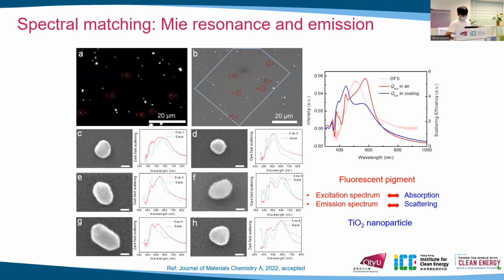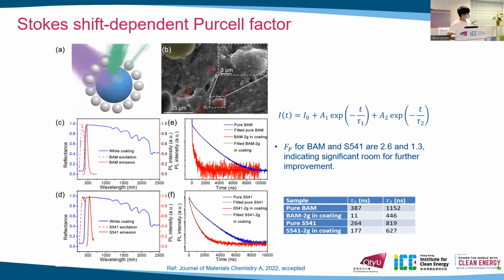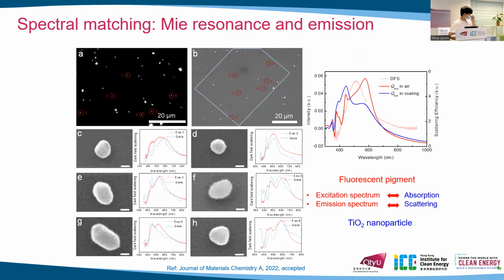And then we can see that BAM has a smaller Stokes shift, so it has a higher Purcell factor. Is it right? As we said, the Purcell enhancement is achieved through the Mie scattering of TiO2 nanoparticles. So we measured the scattering spectrum of single TiO2 nanoparticles. We can find different sizes and shapes for the TiO2 nanoparticles, but the scattering peaks lie a little bit larger than 500 nanometers. If so, S541 should match well with the TiO2 nanoparticles because it has an emission peak larger than 500 nanometers. But this scattering spectrum is measured on a glass substrate.